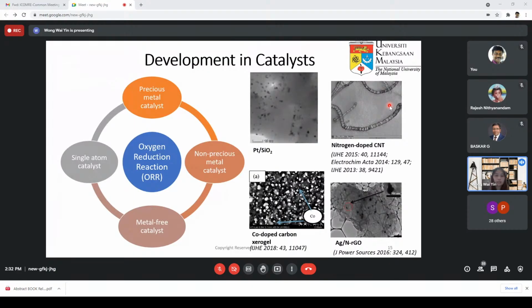For anode itself, there's less study as compared to cathode because at the anode, where hydrogen oxidation occurs, platinum is the ultimate catalyst which has the best performance. There's not much that can be done except trying to reduce the amount of platinum while maintaining the efficiency. But on the cathode side, there is more research, simply because even if we use platinum as the catalyst, the overall potential, that means the efficiency of catalyzing this ORR, is still low. It's still far lower than the anode. The overall potential is about 300 millivolt.